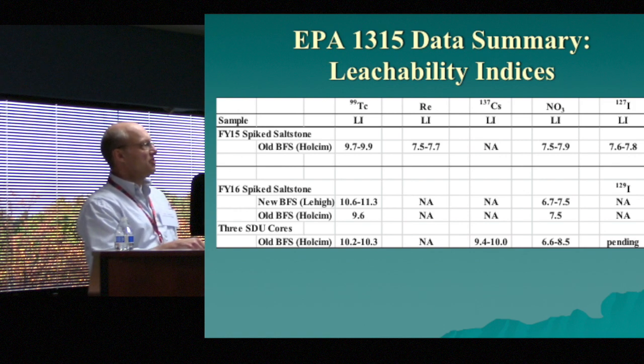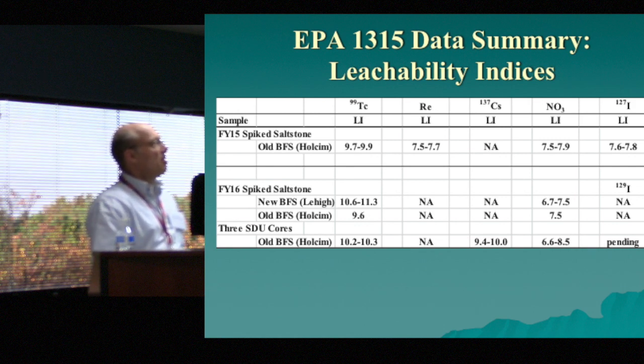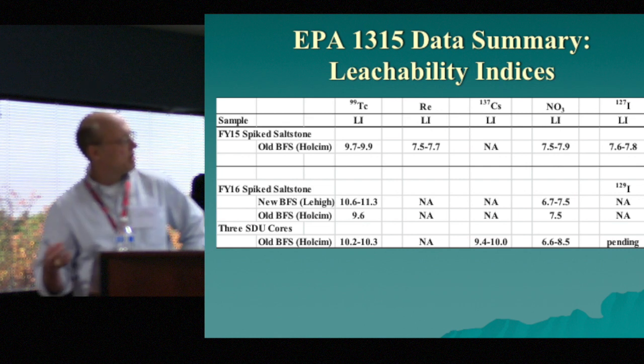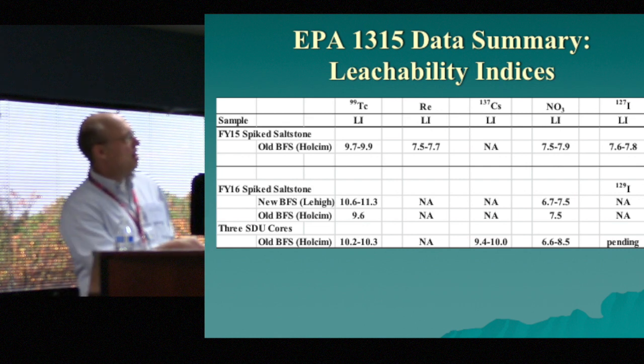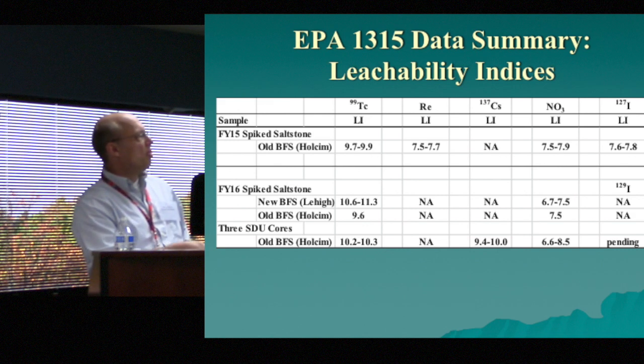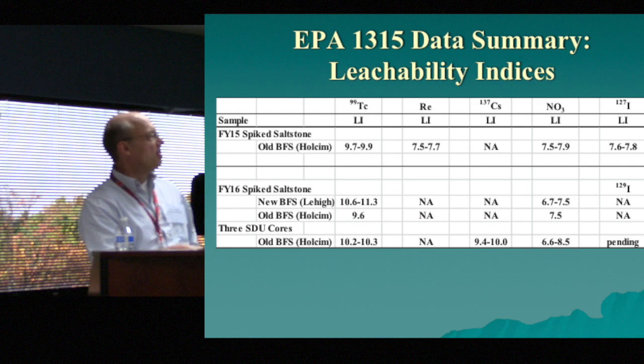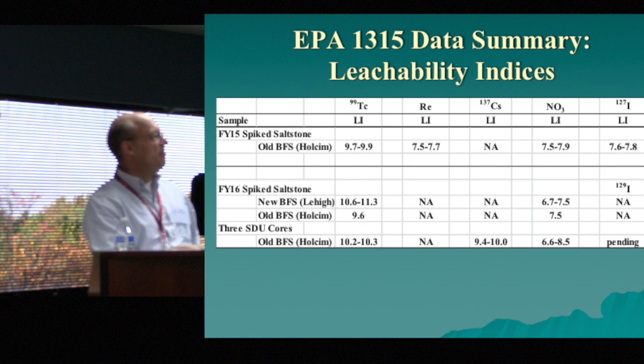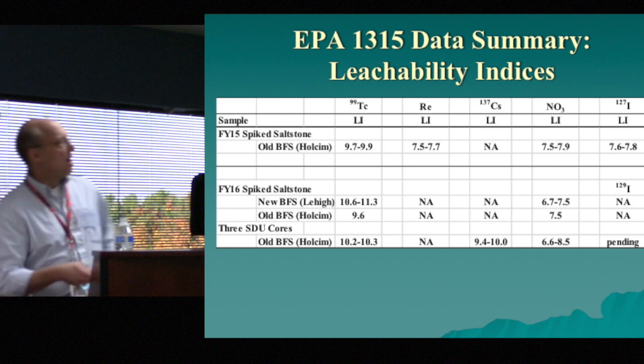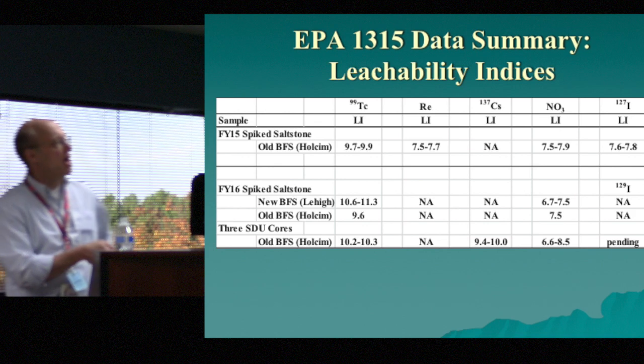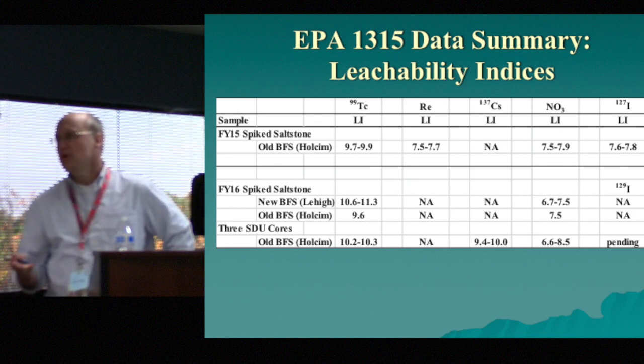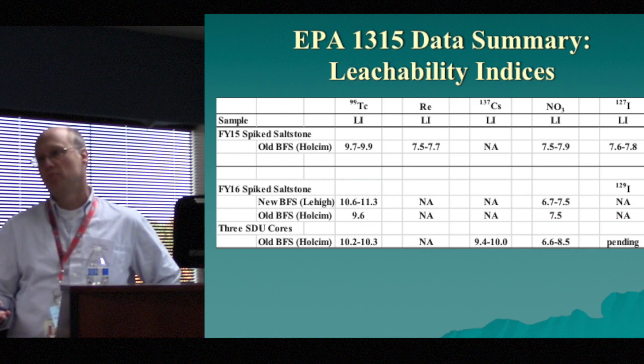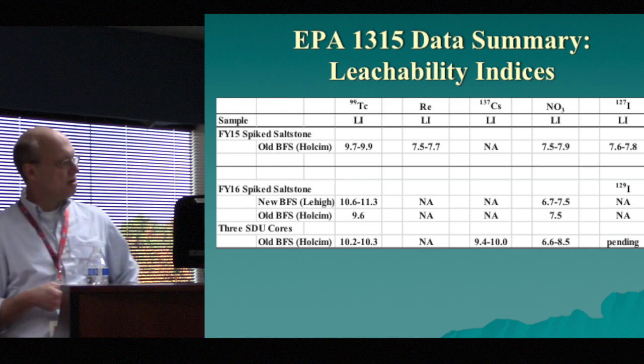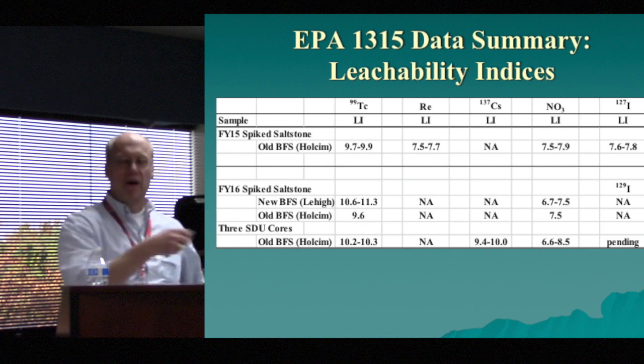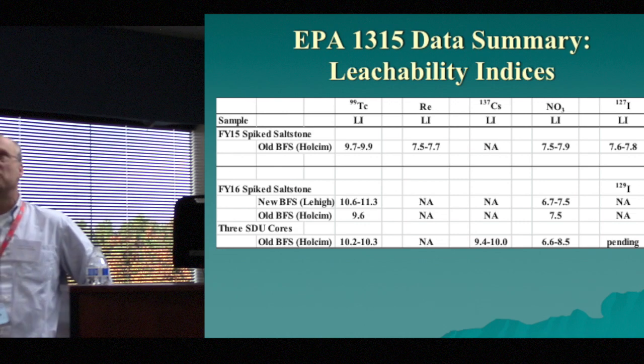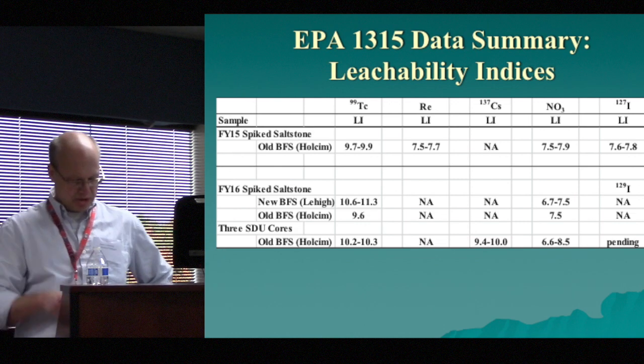If we go down to the new material, as we were talking about earlier, we get quite a bit higher leachability index with the new material. It has a higher reductive capacity than we do with the old. And then also when we go back and look at the 3 SDU cores that we're using, the old material, it actually has an intermediate value, even though it was the older Holcim blast furnace source. What we think is that this has been cured 20 plus months before it was ever drilled out. And so that even suggests that there may be some kind of curing duration effect that we see in this data. The other thing that's important is that a lot of these values are very consistent with values that have been observed in cast stone as well for similar tests. Next slide.